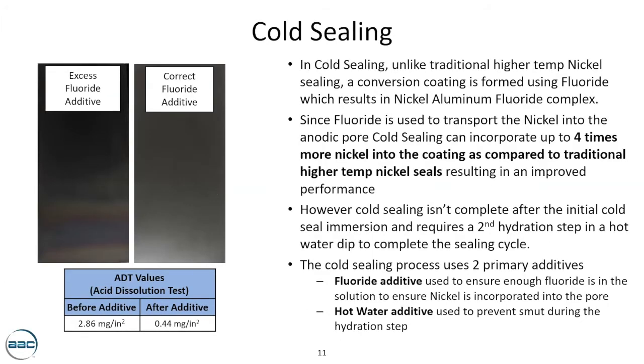All right, now on to cold sealing. So the cold sealing is very different than the sealing we've discussed in the last two slides. The goal of cold sealing is to essentially create a conversion coating that's formed when you have fluoride in a bath. And what the fluoride does is it creates a nickel aluminum fluoride complex that plugs that anodic pore.